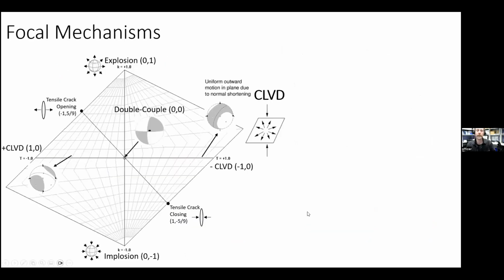So the way these are often plotted is on this thing called a Hudson T-k plot. If you have a shear fracture, that's right in the center of this plot is where it's going to show up. All the shear fractures just show up right in the center. Now you have the isotropic component along this axis. So you have explosion going up, implosion going down. So if it was a pure explosion or implosion, it would be on this line. And then you have your CLVD components along this horizontal line here. But then of course they can have different amounts of these different components, so it could show up sort of anywhere around here.